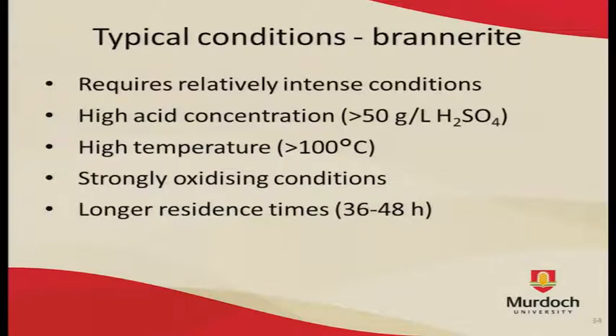Higher temperatures, even pressure leaching has been suggested. But even under these, more strongly oxidizing conditions as well. Even under these conditions, though, dissolution will still be slow. The Canadian mines I referenced earlier leach brannerite in 60 to 75 grams per litre sulfuric acid, about 75 degrees, with residence times of a couple of days needed for adequate recoveries.